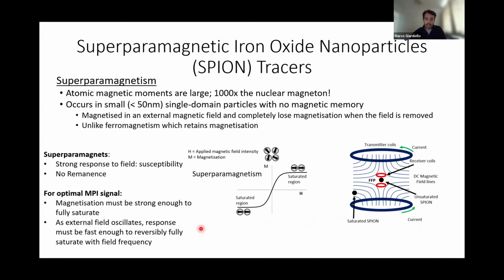So in other words, if that field is going so fast and this does not fully saturate quick enough, so it's not able to keep up with the oscillating field, you wouldn't fully saturate your particle. There would be some kind of resonance or remanence, sorry, of your particle, and you wouldn't get a strong signal. So ideally, what you want is a very responsive particle, with magnetization as high as you possibly can,